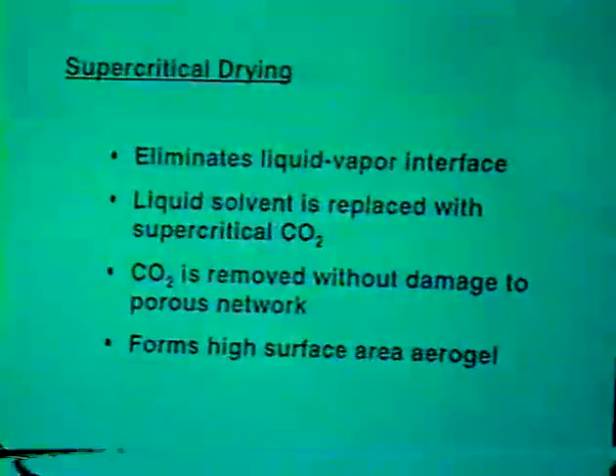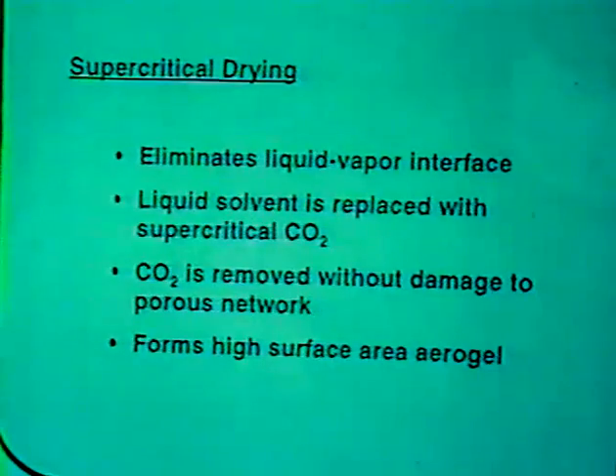CO2 is used to extract the solvent, and then the CO2 is just vented without creating a liquid-vapor interface. One advantage of this is that the integrity of the network is protected in the drying step, and because of it, we can form a high surface area aerogel.